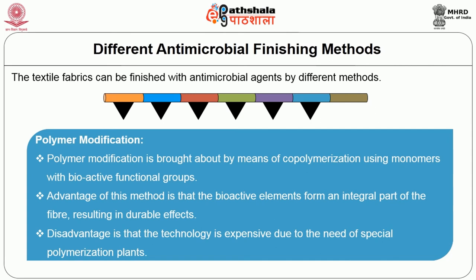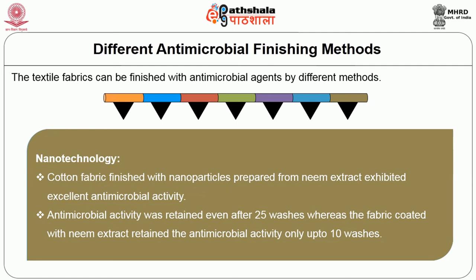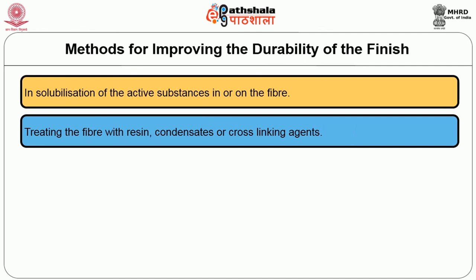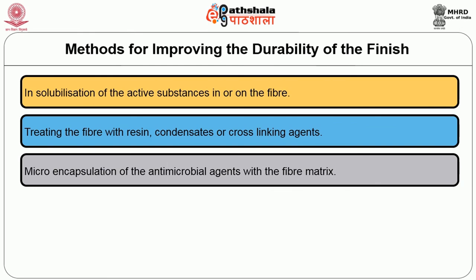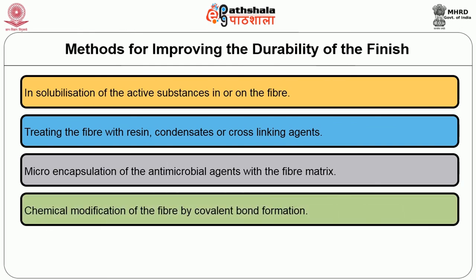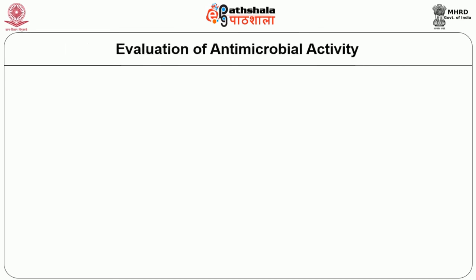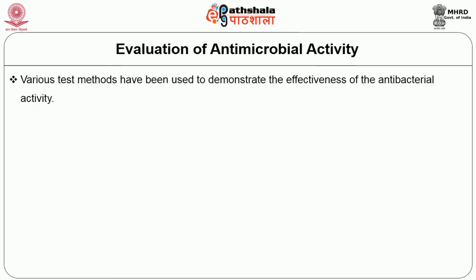Nanotechnology: cotton fabric finished with nanoparticles prepared from neem extract exhibited excellent antimicrobial activity. Antimicrobial activity was retained even after 25 washes, whereas fabric coated with neem extract retained antimicrobial activity only up to 10 washes. Methods for improving the durability of the finish include: insolubilization of active substances in or on the fiber; treating the fiber with resin, condensates or cross-linking agents; microencapsulation of the antimicrobial agents within the fiber matrix; chemical modification of the fiber by covalent bond formation; and use of graft polymers, homopolymers and copolymerization onto the fiber.